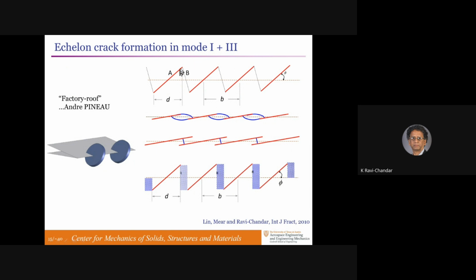Eventually what happens is when these so-called A type of cracks slanting to this side start moving, this ligament between them, depending on how wide they are, they create local tension, and they may do a handshake like this. So this crack curves and comes and meets this one. If they're close enough together, that's how they meet up. In some cases, they just break as a brittle crack perpendicular to the daughter cracks. For us, all we need to know is that when these parent cracks spawn daughter cracks, they're not connected, and there's some energy that is stored in this region, and that needs to be accounted for if you were trying to look for a criterion for crack growth, where only partial crack growth is observed.